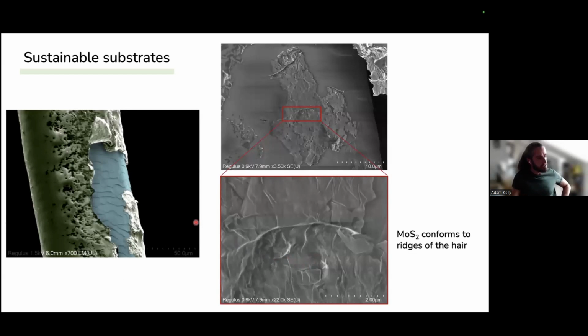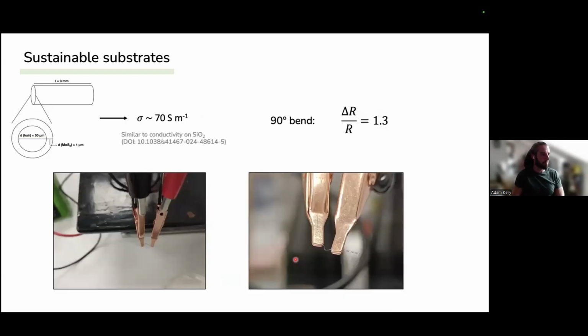We drop cast MoS2 onto hair, and what we found was it actually coated it way, way nicer. So you can see the keratinous structure of the hair along here. We have an MoS2 coating on the outside, and because the MoS2 is large and thin, what we find is really nice conformality onto the structure of the hair itself. So this allows the MoS2 to move with the hair as it bends and stretches.